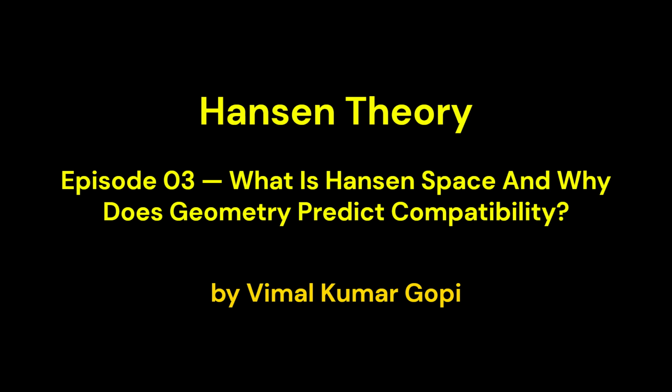Now here is where most engineers misunderstand the concept. They assume the sphere is fixed and absolute. It is not. The solubility sphere depends on molecular weight, polymer structure, temperature, and formulation environment. This is why two acrylic resins can behave differently even if they appear similar on paper. Hansen Space shows you trends, not guarantees. And that is exactly how engineers should use it, as a prediction tool, not as a replacement for thinking.